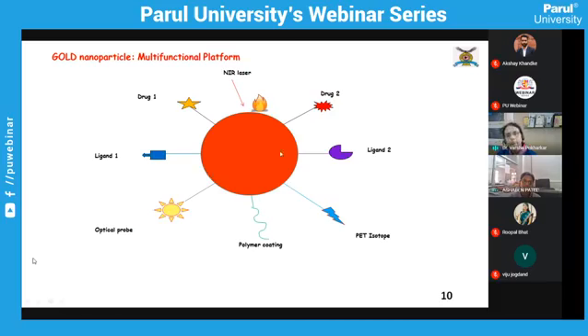And gold nanoparticles per se are also inherently used for phototherapy, where if you shine NIR laser light, they are known to cause local heating and thus cause the destruction of the surrounding cells. So there are several applications that can arise by simply decorating the surface of the gold nanoparticle with the kind of molecules that we are interested in. So we can really design these surfaces very nicely and see to it that we have a system which can be safe as well as efficacious.